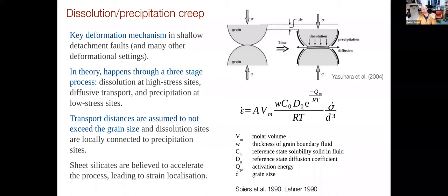This is the exponential term, the stress and the grain size. So it's inversely correlated, to the power of three, to the grain size. Grain size is really important. And that's the takeaway from that component, where the process is affected by dissolution, then transport around the corner, which is controlled by the grain size, and reprecipitation.